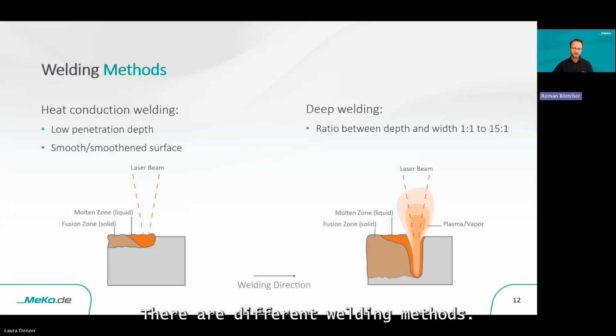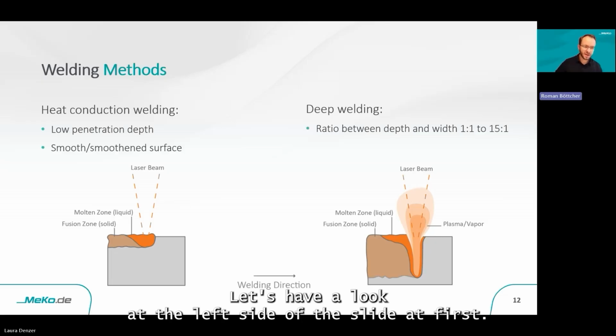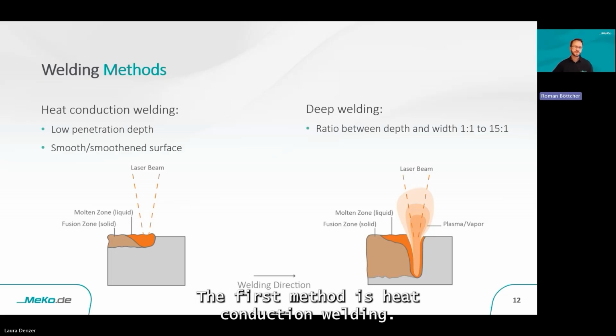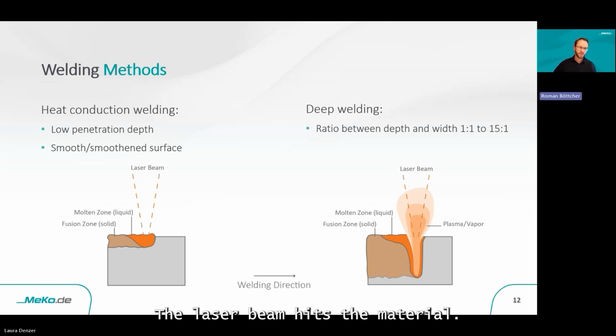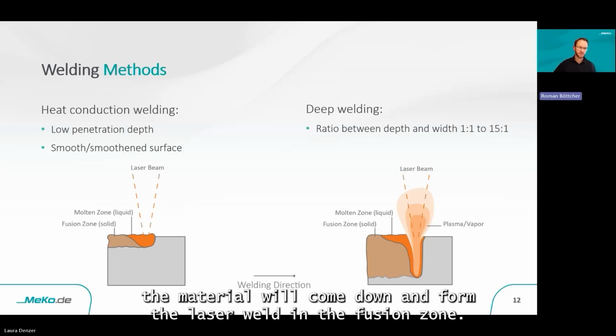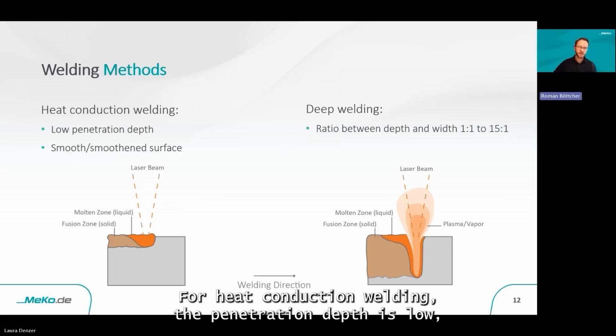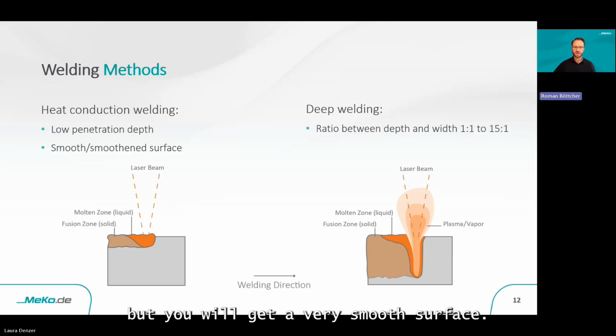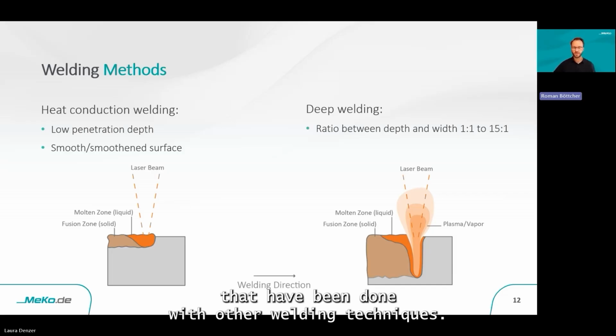There are different welding methods. Let's have a look at the left side of the slide at first. The first method is heat conduction welding. The laser beam hits the material and it will melt. If the laser beam or the workpiece moves, the material will cool down and form the laser weld in the fusion zone. For heat conduction welding, the penetration depth is low, but you will get a very smooth surface. Laser heat conduction welding is often used to smoothen the surface of laser welds that have been done with other